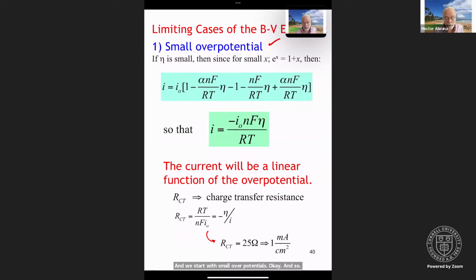And so from a mathematical standpoint, if the argument in an exponent is small, then we can linearize that. e to the x is essentially 1 plus x for eta small. If we do that, then the Butler-Volmer becomes I equals I0 times [alpha nF eta over RT minus 1 minus nF eta over RT plus alpha nF eta over RT]. What cancels here? The ones cancel and the alpha nF terms cancel. So you're left with I equals negative I0 nF eta over RT.